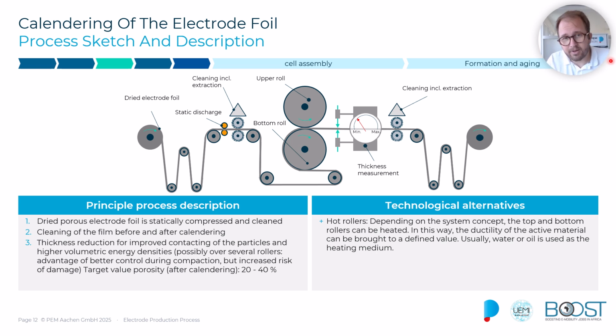Typical values here to maintain a certain line pressure could be around 2,500 Newton per millimeter, but also calendering speed normally is quicker than the coating speed. So normally the calendars work quicker than the coaters. So you can normally use one calendar, one slitter here after the coating process. To just give you an understanding on how much impact the calendar has, the porosity can be reduced from around 50% after the drying process by the calendering to around 20 to 40%, and that's defined by the gap width you leave between the two rollers and the pressure you create.